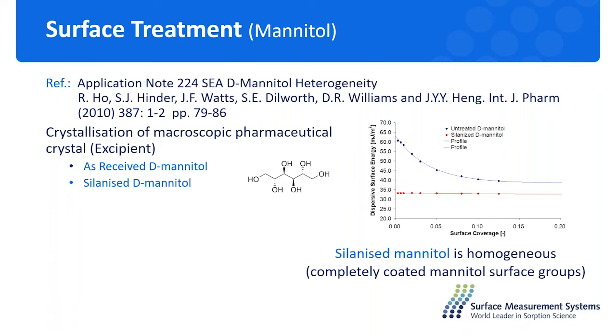So this time, the surface energy is not changing with the surface coverage, and both the low energy site and the high energy site are almost at the same level. The surface of this treated mannitol is more uniform, and with the silanization, you change the surface energy to a lower value that basically passivates the surface, with a more stable flow behavior of this particle material.